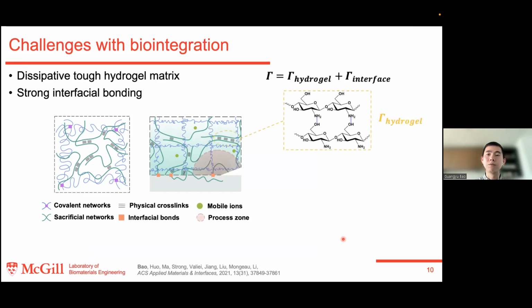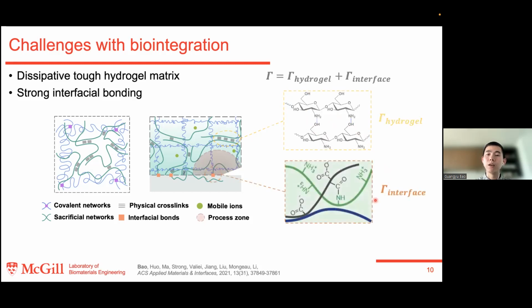As can be seen from the equation here, the total adhesion energy is the summation of the energy dissipated from the adhesive hydrogel, and also the individual bonding strength at the interface. So to amplify the energy dissipation, we can use a tough hydrogel which has a dissipative mechanism, such as a hydrogel containing a sacrificial network, which has hydrogen bonding and can amplify the background hysteresis. And at the interface, we can use covalent chemistry crosslinks, such as carbodiimide chemistry, to covalently fix the hydrogel to the tissue to ensure a reliable wet interface.